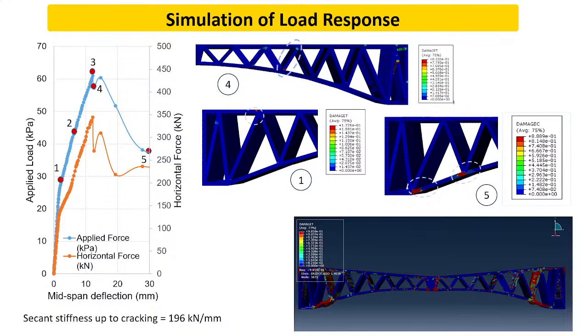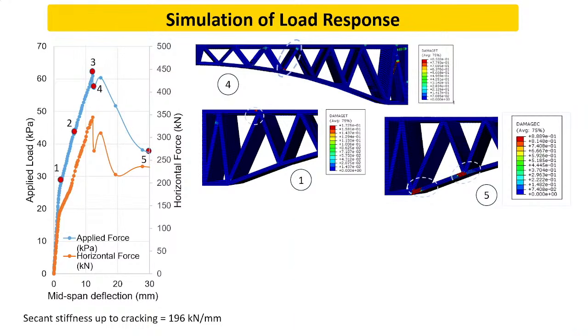And while it went from point 1 to point 3, there was a lot more cracking, a lot more diagonal members cracked, and there was a little bit of residual stress that the tension wire was providing. The final failure happens because of the compressive strut. When the compressive strut fails, one of the members that's loaded in compression, the structure goes. So it gives us a reassurance that even with a little bit of tension reinforcement, for a structure that's optimized and puts concrete in compression, I can actually design structures that can take a significant amount of load.